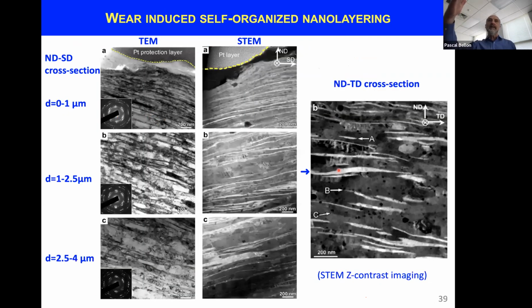You see it from the top surface. This is a series of TEM, STEM micrographs through the thickness away from the wear interface. And you can see that here over microns, this material that started with equiaxed silver precipitates chose to form self-organized nano layers, a little bit like phyllo dough, at the scale down to maybe 10 nanometers at the very top. And this layered structure has very good wear resistance, we think, because it provides a very good resistance to crack propagation into the material. So it wears, but the wear debris or particles are very small, and therefore the wear rate is small. And plus, it generates beautiful microstructure, as you see on the right-hand side.